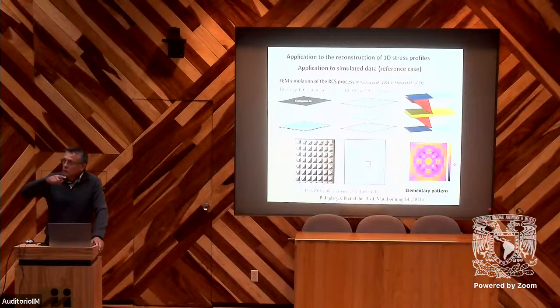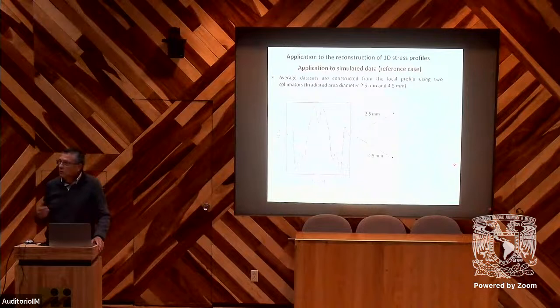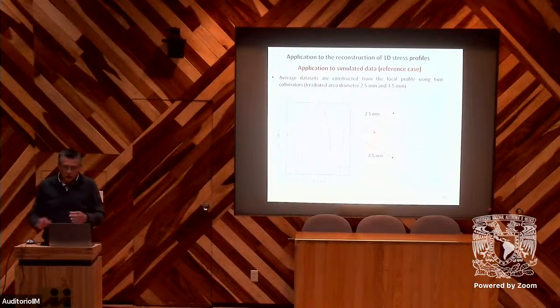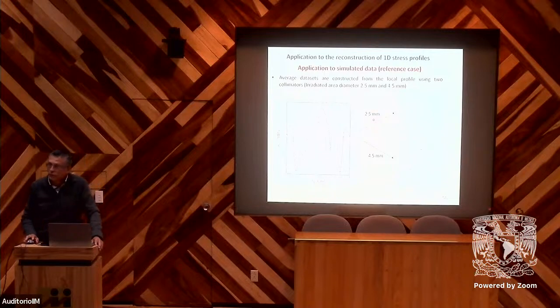If we consider a line, we will have some variation of the stress in this pattern. These are the results of the calculation from finite element analysis of the residual stress in one line. So the problem is, if we use a spot size of 2.5 millimeters or 4.5 millimeters, we will have an averaging effect. That means if we measure in different points, for example, with a very regular grid, for the higher size we have very high averaging. So the question is how to determine this profile from these profiles.